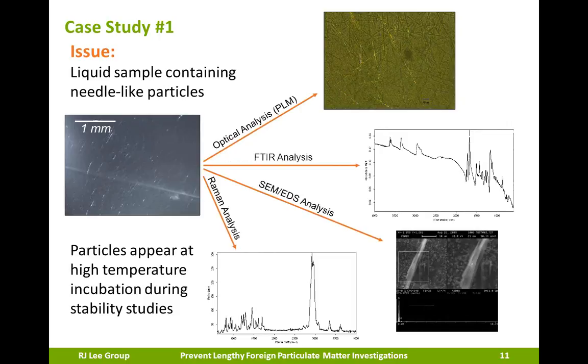For the infrared analysis, we used a reflectance micro FTIR technique and obtained a spectrum. For those of you who are not familiar with the FTIR, the peak annotations that you see identify functional groups in the material, and then that's what helps you to make an identification. For the scanning electron microscopy, so SEM, again you can see the crystal-like morphology at very high magnification.